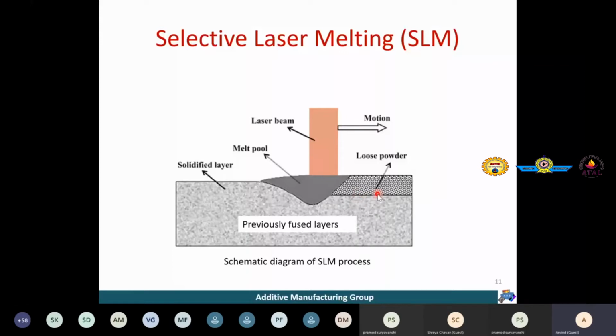We can see clearly that as the laser beam traverses, it creates a local melt pool, and as the laser traverses further, the local melt pool re-solidifies to create a consolidated layer. So we can see different kinds of physics: solidification here, then the interface of melt pool and powder, then the melt pool where convection patterns and convection flow of the molten metal can happen, right? The laser is interacting with molten liquid. Here the laser is also interacting with some powder, right? So it is a complicated scenario involving several physical phenomena.